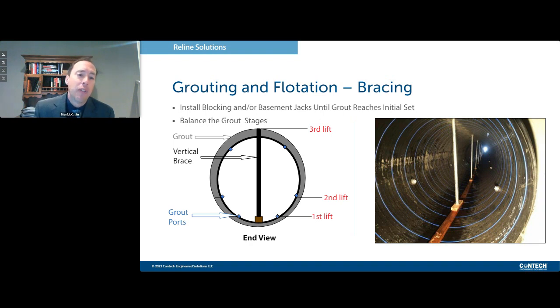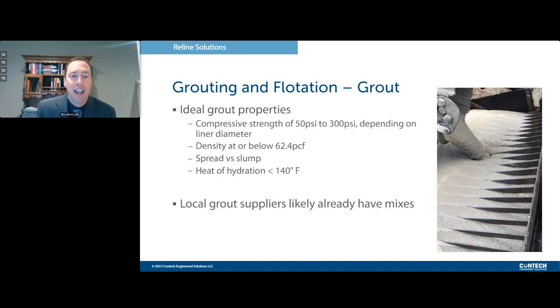In the detail on the left, you can see that the grouting is done in lifts. So you're not doing one giant grout, you're doing two or three different lifts based on the grout density and the slope of the pipe and pipe diameter. We can help the contractor with that.